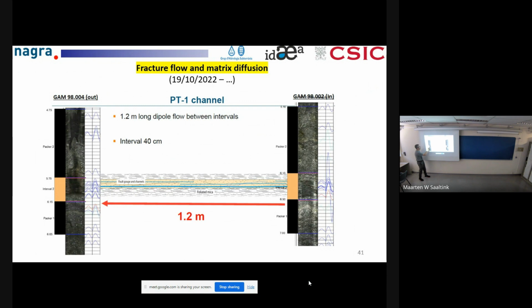So in this central area, this is a shear zone, a highly deformed part of the granite, and this shear zone has quite a high concentration of brittle fractures. This is the part we're concentrating on. The rest, we have packers separating those areas, so the flow does not affect these parts. So basically we concentrate on this fracture, with one injection borehole and one extraction borehole. Distance is 1.2 meters.